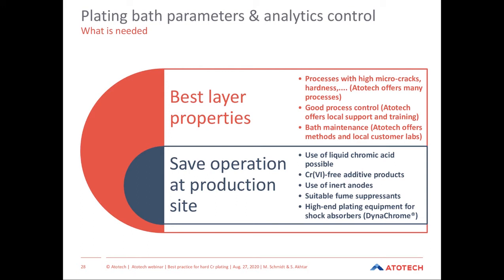So we support customers with the switch from typically used solid chromic acid to liquid chromic acid to avoid the dust and the chrome 6 dust inside the plating shops. We have chrome 6 free additive products to be added. We also support with the use of inert anodes in order to avoid the sludge generation of the lead tin anodes. We have fume suppressants to keep the emissions on a controlled level.